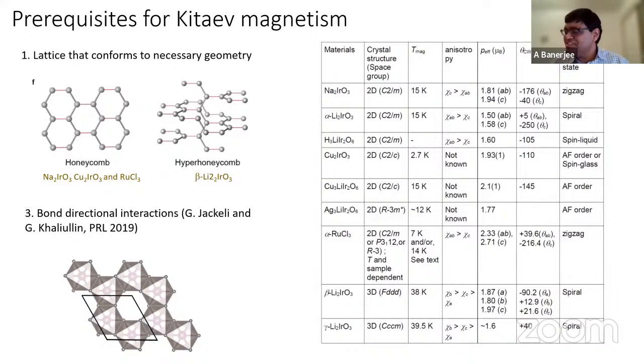So that brings us to the question that, okay, fine, it orders, but do all the spins order? Can we still get some signatures of quantum spin liquid remnant, even if you have some of this order left in the system? That is some of the questions that we started asking. And this is how we got to this material called alpha ruthenium trichloride, where we found that the frustration factor is actually almost a factor of 10, which means that if all the spins would have ordered, it should have had a Néel temperature of almost 100 Kelvin, but it has a Néel temperature of 10 Kelvin. So there are a lot of spins which are basically disordered, and there is probably some kind of spin liquid behavior going on there.